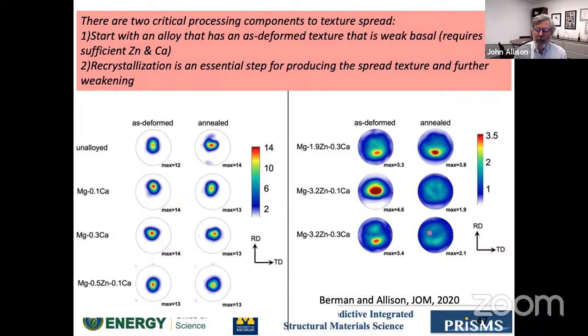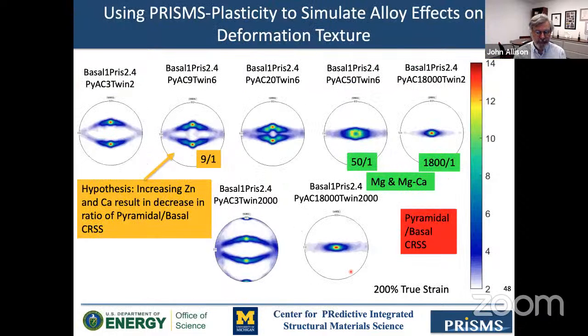But another important part of this is the recrystallization after deforming. So she did all these experiments using a Gleeble to simulate rolling. These are very complicated 10-step rolling simulations, followed by short anneals. And we've theorized that this was because of this reduction in the ratio of pyramidal to basal.